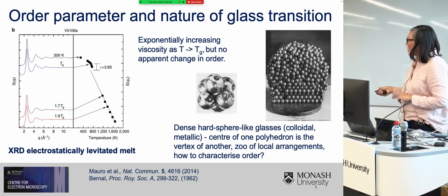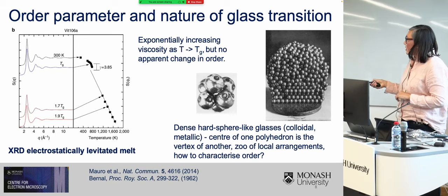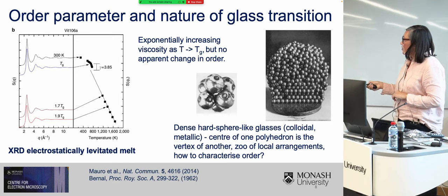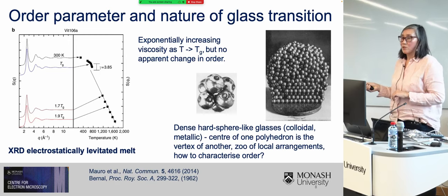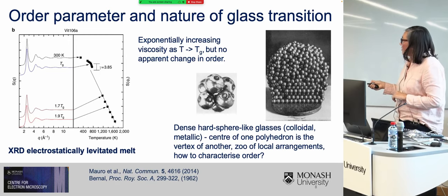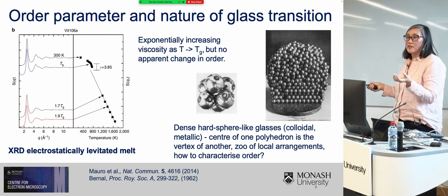So here's a concrete example of this for a real system. This is an X-ray diffraction measurement on an electrostatically levitated melt. It actually happens to be the commercial metallic glass Vitreloy 106. And you can see that as we cool the system down through this glass transition Tg, the order that you can see in the structure factor does not really change that much at all. And yet here in the vicinity of the glass transition, the viscosity exponentially increases.